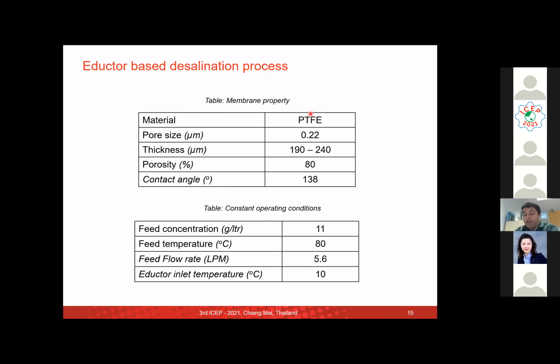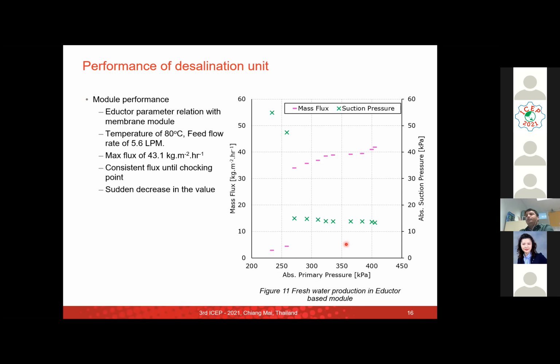The experiment was done with a PTFE membrane with a feed concentration of 11 grams per liter of salt, and the feed temperature of the water was 80 degrees Celsius. The result was promising compared to existing systems of this kind, where we could get water of up to 43 kg per square meter per hour when we operated the system. This pink line here is the mass flux, and the green line is the pressure at that particular condition in the suction chamber. So it is creating a sub-atmospheric pressure condition on the inlet suction tube, which ensures that there is enough vapor pressure difference to drive the vapor inside the eductor.